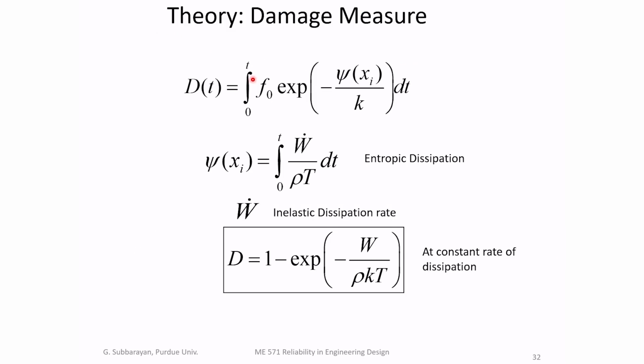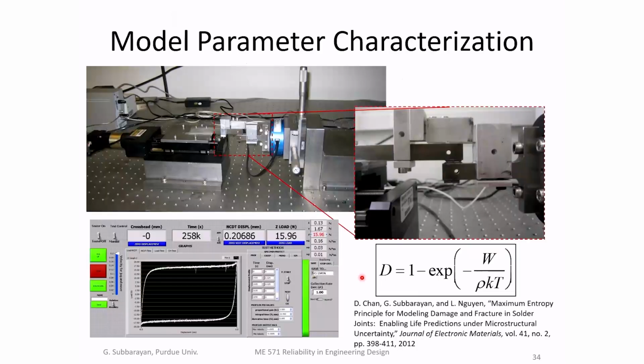And what that predicts is that a material at any point would accumulate damage according to this distribution. And this is actually an exponential type distribution. This particular model is inspired by the theory of statistical mechanics, physics, thermodynamics. So this W here is dissipation, and K is some parameter that's inspired by the Boltzmann distribution, the Boltzmann constant. And it turns out that K can be extracted. That's the single parameter that predicts how fast or how slow the crack would grow. You can extract that by isothermal mechanical tests in the lab, which is what we did.